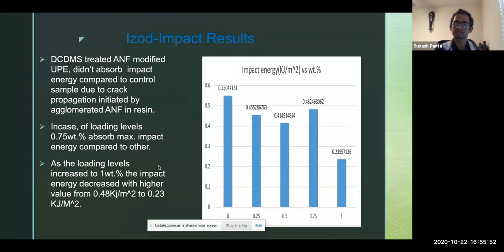Izod impact results. Dichlorodimethyl silane treated aramid nanofiber modified polyester didn't absorb impact energy compared to the control sample due to crack propagation initiated by agglomerated aramid nanofiber in resin. In case of loading levels, 0.75 weight percentage absorbed maximum impact energy compared to others. As the loading level increased to 1 weight percentage, the impact energy decreased from 0.48 kilojoule per meter square to 0.23 kilojoule per meter square.